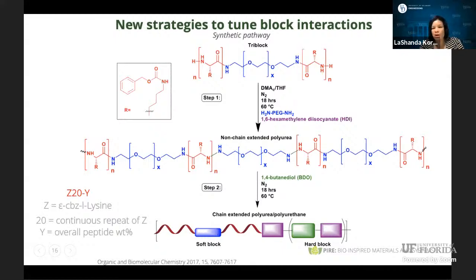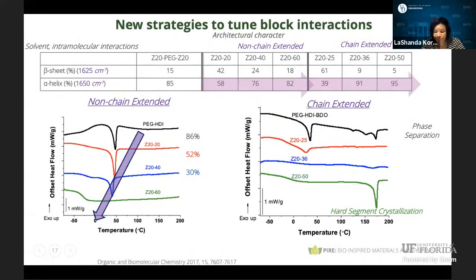In this case, we make our tri-block structure using N-carboxy anhydride polymerizations. And then we make our non-chain extended systems. So that gives us our first comparison. If we then use 1,4-butanediol, we can now make our chain extended system where we build up both the soft and the hard block, with the identification shown at the bottom. In this case, we're focused on the alpha helical materials, and we've chosen a repeat unit length of 20 for our lysine. And what we're modulating is the overall peptide weight fraction.